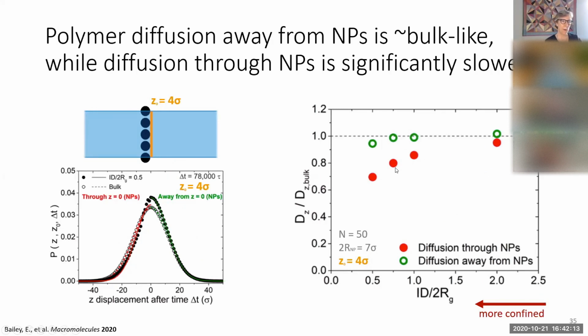So this is all for the same molecular weight. But if we had a higher molecular weight, so if we had this set of data, and then we mixed it with a larger polymer, we would have this set of data. I don't know what would happen. I don't know whether that local environment would cause a partitioning of the different polymer molecular weights, because squeezing between the particles is easier if you're a short chain. It's less of an entropic penalty. And I don't know if the polymers would stay mixed.